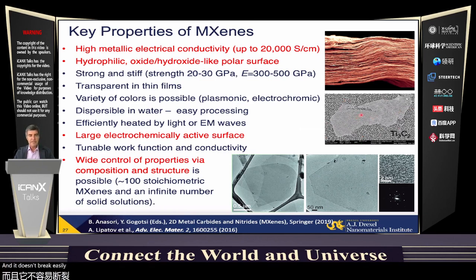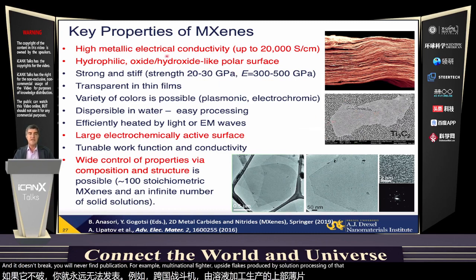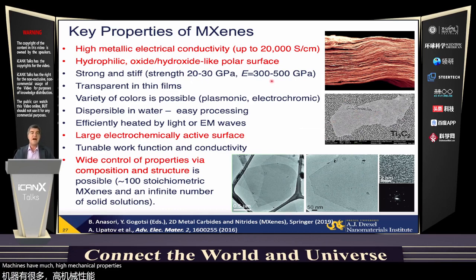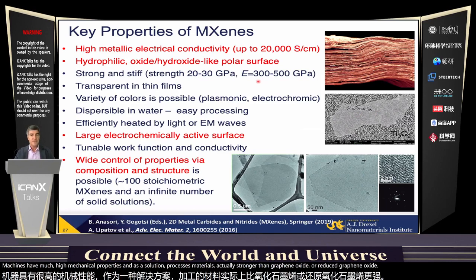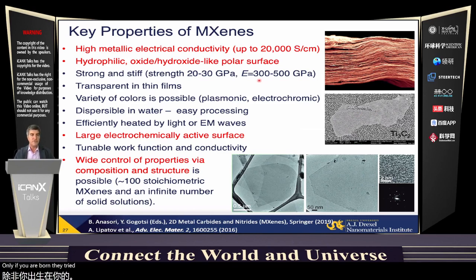You will never find a publication, for example, of molybdenum sulfide or oxide flakes produced by solution processing of that size, because of mechanical properties. MXenes have much higher mechanical properties than other solution processed materials, actually stronger than graphene oxide or reduced graphene oxide. Only pure boron nitride or graphene separated from single crystals will outperform them here. They also have a variety of plasmonic colors that you could see on my first slides here. And again, tunable properties by changing the M and X, number of layers, ordering of elements in the layers, and surface termination. And this is what gives a lot of properties.